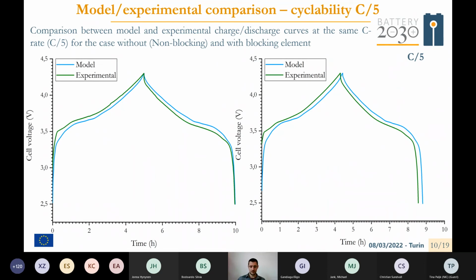We also ran the model at higher C rates, where you can see, as expected, that the interfering effect of the element accounts for more as you increase the C rate. Unfortunately, it was difficult to assess this experimentally because at high C rates, the coin cell used to validate the model didn't perform very well, so we report only the comparison at C/5. But the model was also run at higher C rates, highlighting a more appreciable effect of the interfering elements.